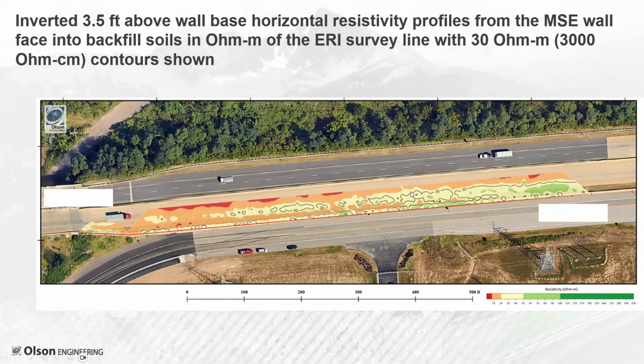And I believe that towards the median, that data might not quite be real because you have this air void affecting your model. And we see that in general, most of the rest of the data is within this 30 contour, at least on the right side. So you should be able to extend that sort of information towards the deeper side. The other factor here is that the MSE strap should only be going, I think, 20 feet into the wall. So we're not caring too much about information past that.